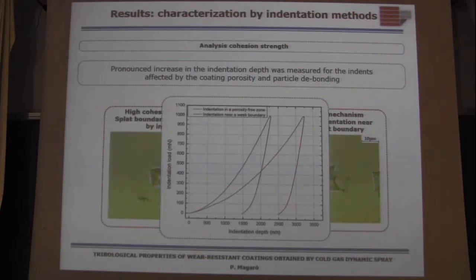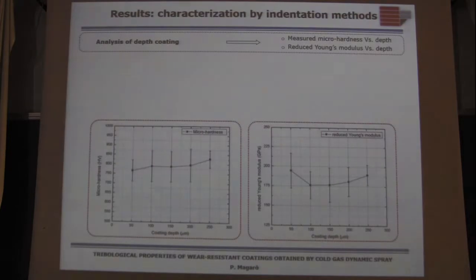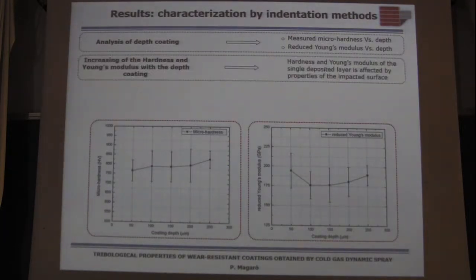In fact, in this zone, a pronounced increase of the indentation depth was measured for the indents affected by coating porosity and particle de-bonding. On the other hand, the analysis of the microhardness and of the reduced Young's modulus was carried out on the cross surface as a function of the coating depth.